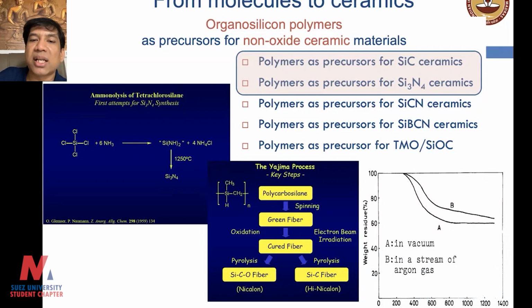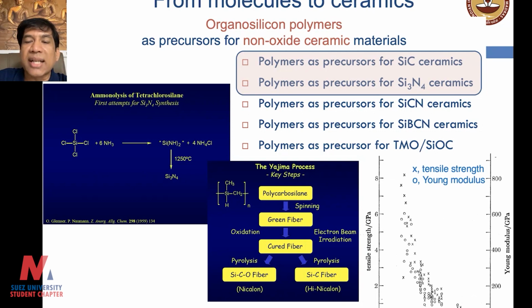For example, to make silicon carbide fiber, you need to produce polycarbosilane precursor, and you should know how to spin it and convert them into silicon carbide fiber. If you are not from the field, you may want to know that the silicon carbide fiber is important as reinforcement in silicon carbide matrices if you want to produce CMCs based on SiC and SiC, which many countries are not able to make as of now because silicon carbide fiber is not available and not many people can make them. However, as I said, the papers are there, but not many people know how to make it.